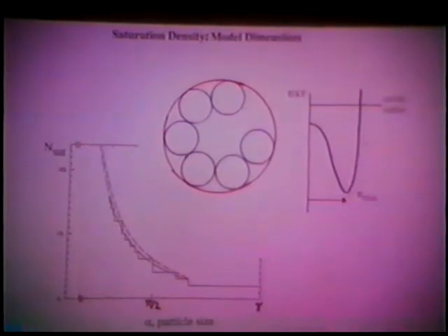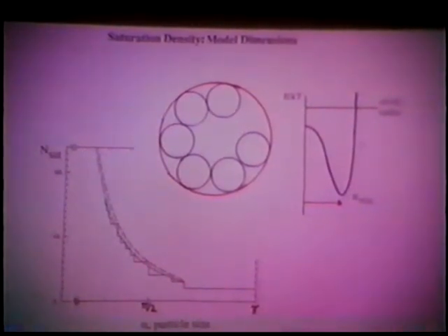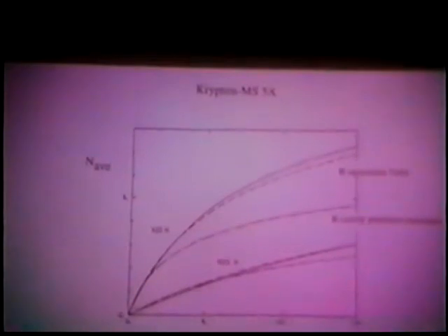But luckily that calculation has been done for us. It appears in the mathematical literature. And given the saturation density of a zeolite cavity, I can use one of these estimates for the size of the particles. The stepped curve are exact results, and I also plot two continuous curves that might be more convenient to use to determine the particle size for a given saturation density. So with this, we can calculate absorption isotherms again.